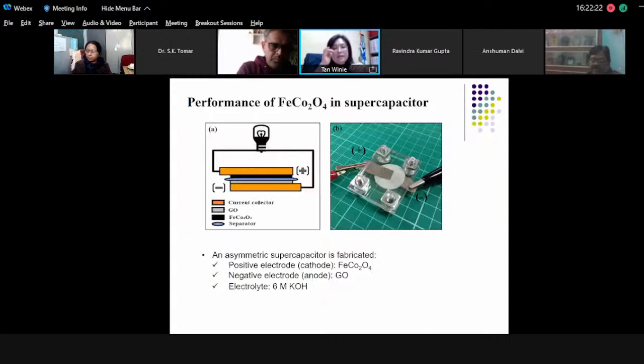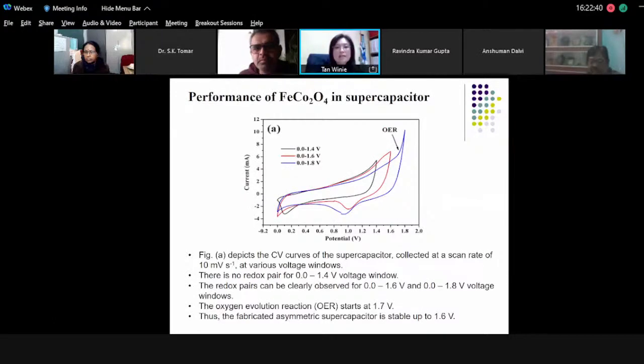And this is the performance of the iron cobaltite in a supercapacitor. We do an asymmetric design, with the iron cobaltite nanosheet as the positive electrode, graphene oxide as the negative electrode, and 6 M KOH electrolyte. Again, this is the CV curves of the supercapacitor. We have the oxygen evolution reaction, OER, starting at about 1.7 volt. So the fabricated asymmetric supercapacitor is stable up to 1.6 volt.